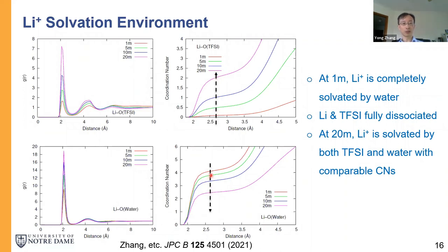Opposite trend for water: at low concentration, each lithium is coordinated by four waters, while at high concentration it is about two. So at high concentration, lithium is really shared by both water and TFSI.